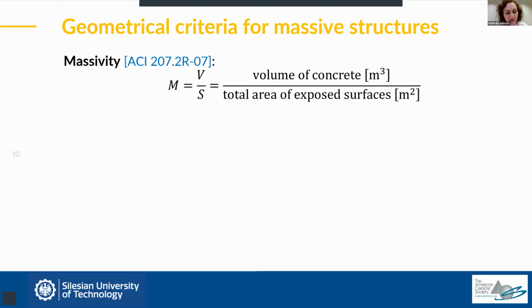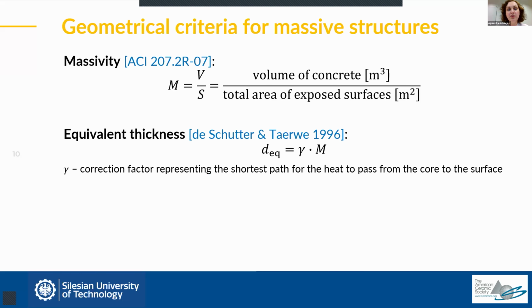This measure has been improved, let's say, by Schutter, so this is an element of a European approach for more complex shapes, because of course, if we imagine a prism, then understanding this ACI definition is very straightforward, but for more complex structures, another measure was proposed which also used some correction factor, which represents the shortest path for the heat to pass from core to the surface.